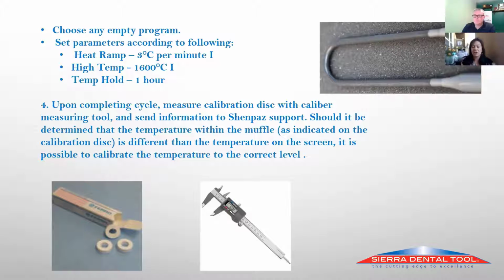That ring is going to shrink. You're going to measure it with some calipers, and it's best to use a digital measuring device. Based on the shrinkage, you will have a conversion chart, and that will tell you how far off your furnace is. Usually they're a little cooler than they should be, because as the heating elements age, they start to lose their ability to conduct heat.